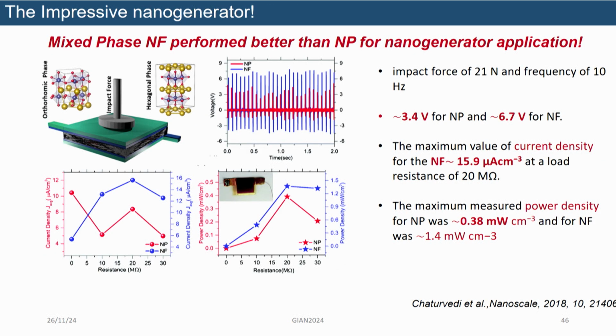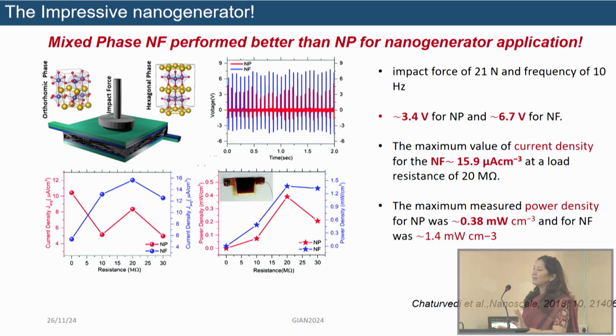So, we tried to look into the triboelectric nanogenerator application, and an impact force of 21 Newton and frequency of 10 Hertz we used to create the impact, and we realized that we can generate 3.4 volt for nanoparticles, and we could generate 6.7 volt for nanofibers, right. And the maximum value of current density for nanofibers is 15.9 microampere per centimeter cube, and for nanoparticle it was 0.38, and the power density was in milliwatt per centimeter cube.